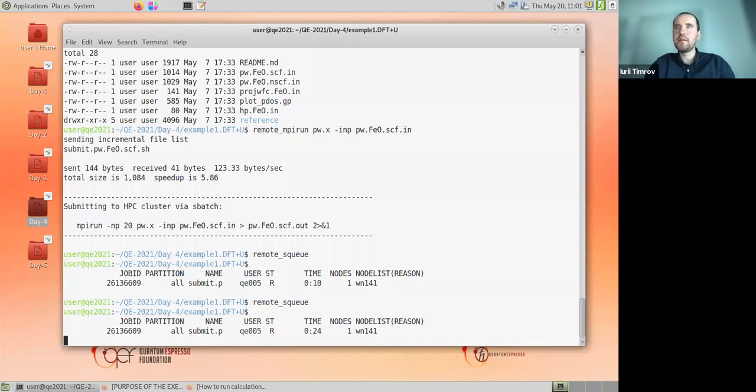Next, mixing pseudopotentials from different libraries. Is it okay? And different norm-conserving, ultrasoft, PAW? Yes, this is okay. You can mix pseudopotentials from different libraries and even different types of pseudopotentials. You can use norm-conserving with ultrasoft. What you cannot do is to mix functionals. For example, for iron you use LDA, and for oxygen you use PBE. That is not possible. But as long as you use one functional, you can mix pseudos.